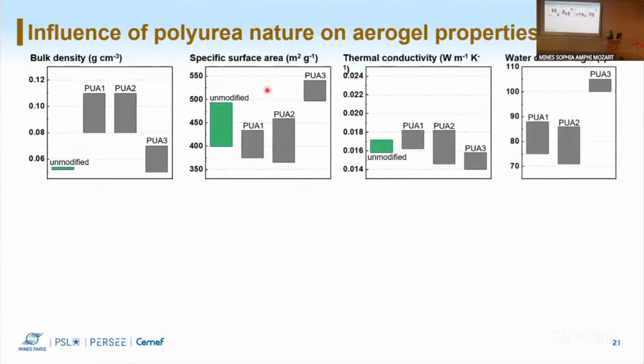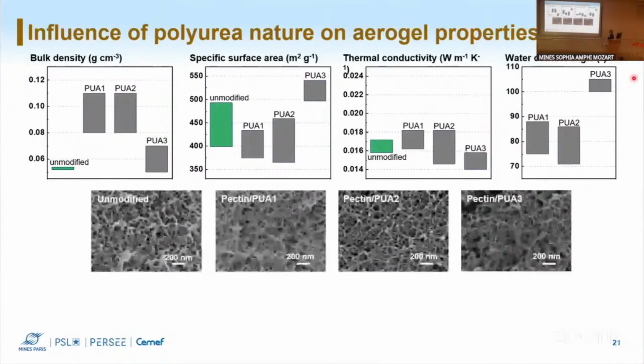And lastly, to evaluate the hydrophobicity, we measured the water contact angle, and we can see that for the first 2 composite materials, we have increased the hydrophobicity of our structure, but we're still not very hydrophobic, so we're below 90 degrees. However, with the third type, we are hydrophobic. Looking at the structure of our material, we cannot really see a difference. The first picture is the neat material, and then there are the other composites with similar concentrations. We cannot see a secondary network or any particulate form, so we suppose that we have a nice coating around our pectin fibrils.